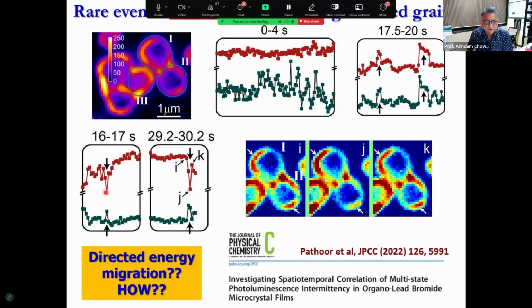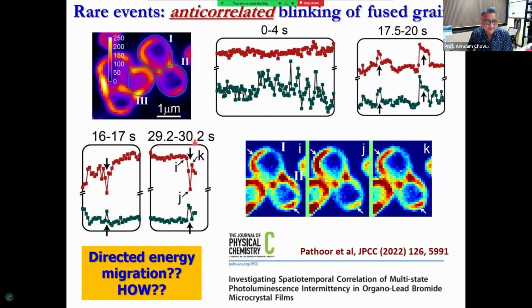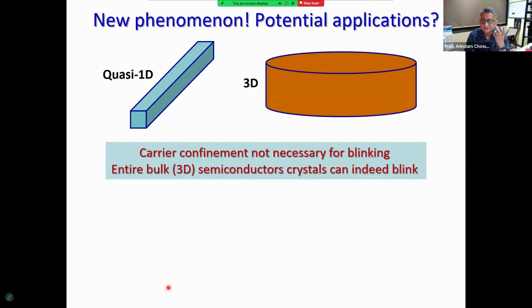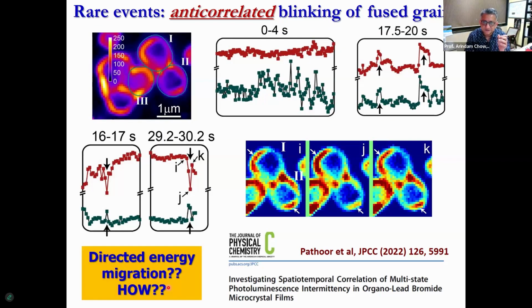But you see what's happening between 16 and 17 seconds and 29 and 30.2 seconds. There seems to be anti-correlated behavior. So it almost looks like, and it's also visible from the images, there's some sort of directional energy flow, carrier migration from one grain to the other. Now, I cannot explain why such a behavior would be observed, and I still do not have a concrete explanation for that. Currently, we are also exploring another option, but that is something that I think I should not discuss in the interest of time.